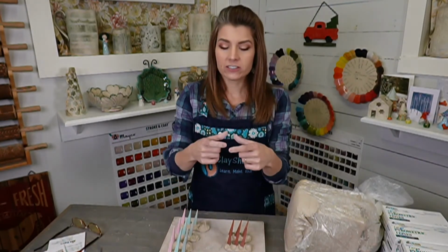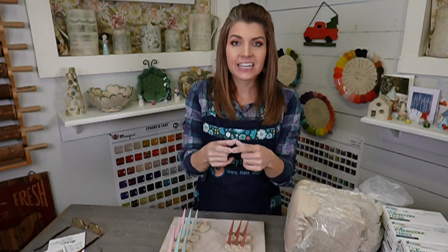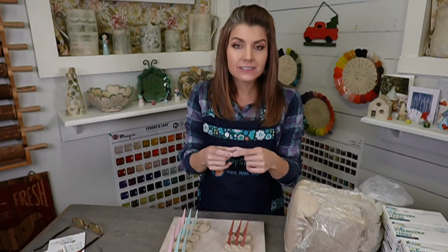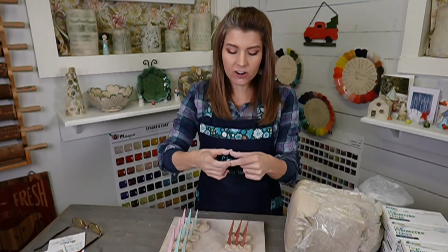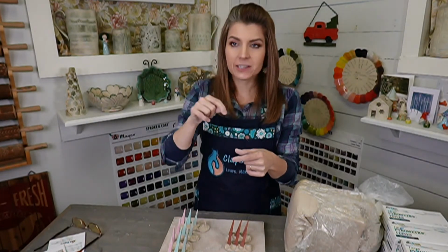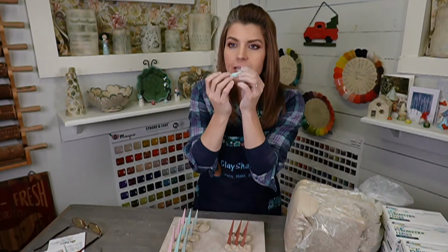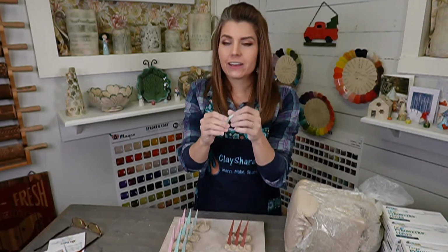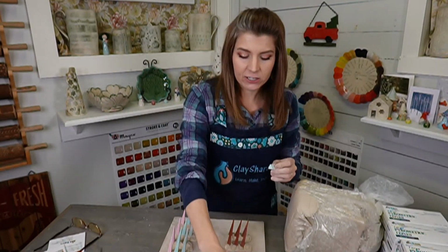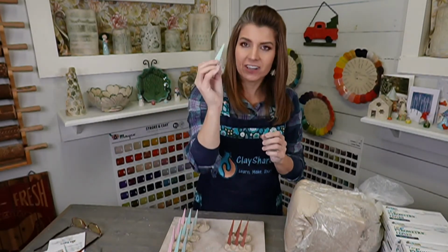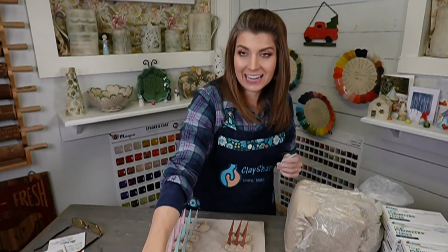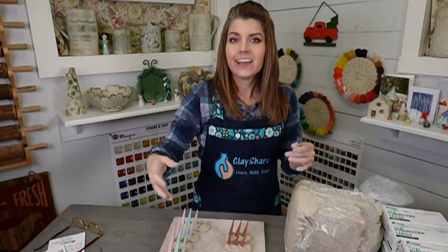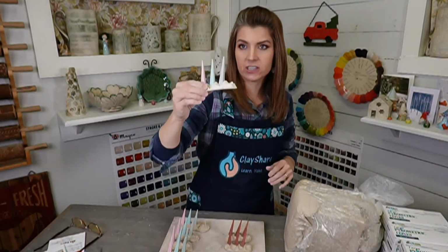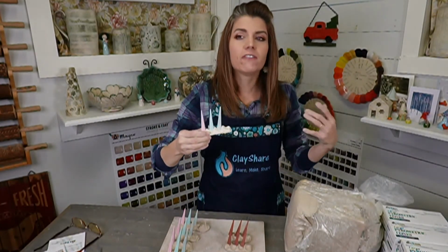Yes, they are. They're often called cone plaques, P-L-A-Q-U-E, or cone tiles, depending on where you're buying them. They are a little piece of ceramic material that has a triangle-shaped place for each cone to sit in. My friend who owns the Saratoga Clay Art Center, Jill Kovacic, uses the cone plaques. I know because I did my residency there and we used them. So you don't make your own cone packs, you just use those little tile things. They are really handy if you do a lot of firings and you don't want to make a bunch of these, because you buy those plaques, you just have to have enough of them for your kilns.